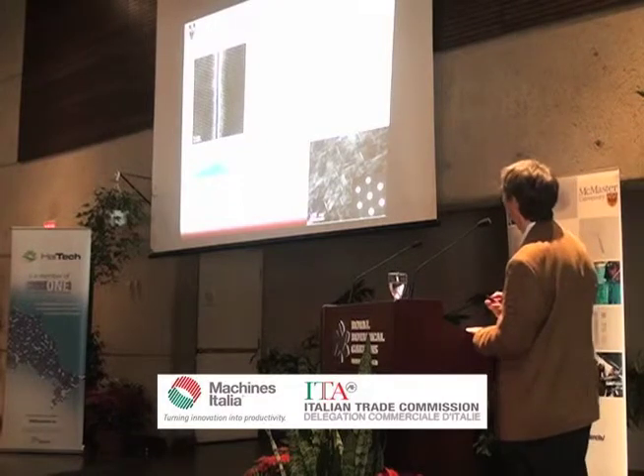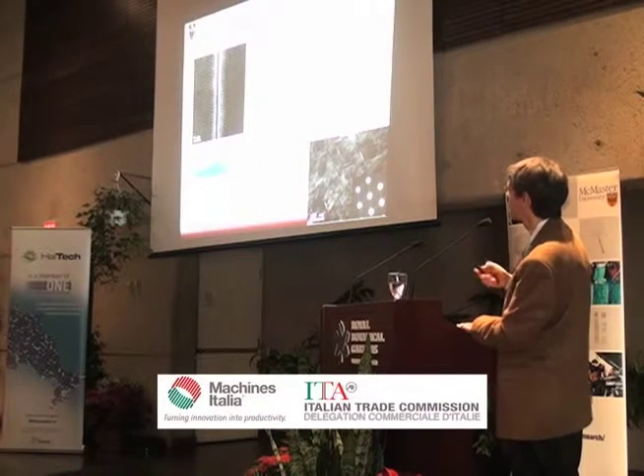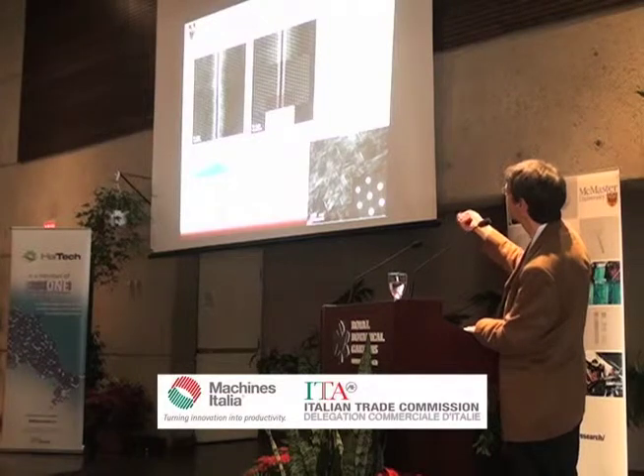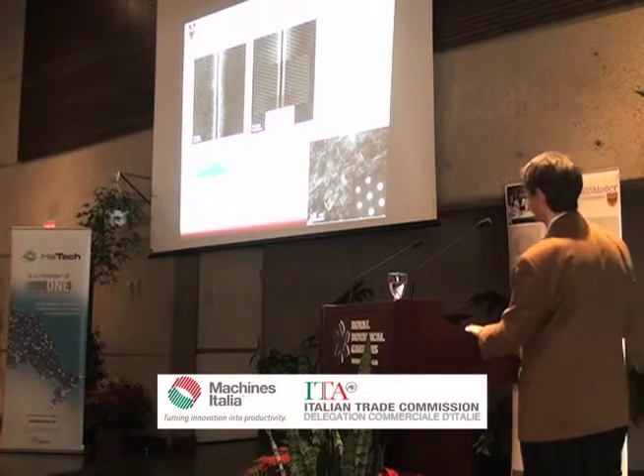These are lightweight alloys. They're used for other applications in aerospace. It's more for parts that don't need to go to high temperature, but it's a very light material and it needs to be strengthened. So it's used in the Airbus A380, and the reason why it can be used is because of additions of lithium and copper that form precipitates, very small inclusions of particles that are as thick as a few atomic layers, and we're able to show them just because of the imaging technique. We're able to show how these are structured, and we did a combination of chemical analysis and simulation to demonstrate that the model we put forward for this type of structure is really consistent with the experimental images.